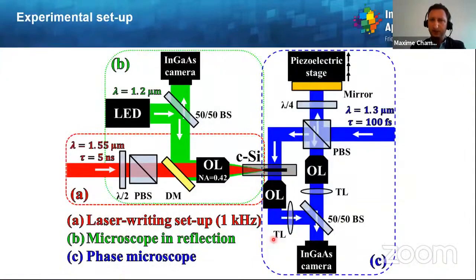So in order to investigate the influence of nanosecond pulse irradiation inside silicon, we have developed another setup relying on 1.55 micron wavelength pulses at 5 nanosecond duration. Then, same as previously, we adjust the pulse energy with a half wave plate and a polarizer, and we use the same microscope for positioning the geometrical focus with respect to the sample.